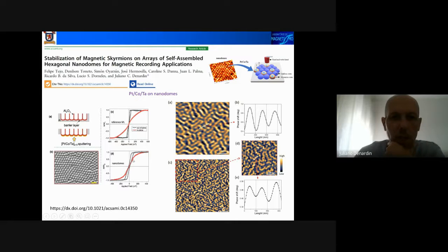And on the nanodomes, we observe that out of plane we have a higher coercivity. We no longer have these two larger parts of the curve, very typical of the multilayers. We have this behavior in a much weaker form. The anisotropy also decreases, and the in plane and out of plane curves are more similar.